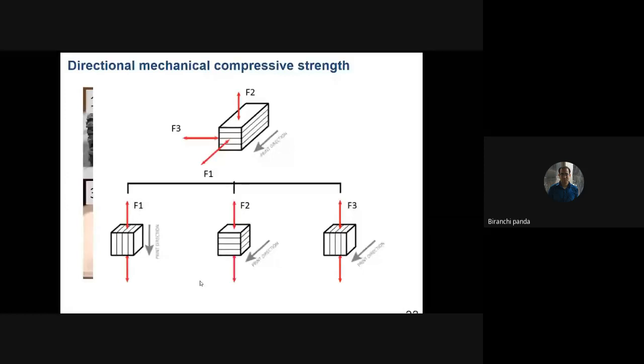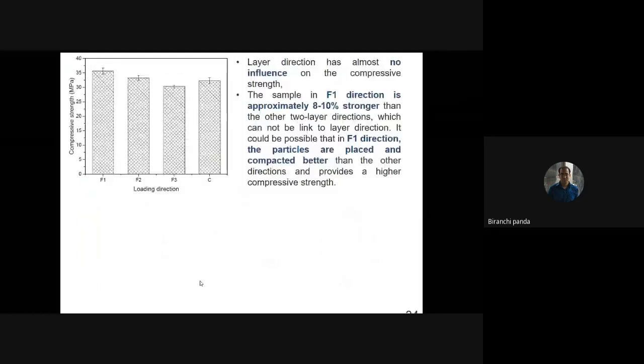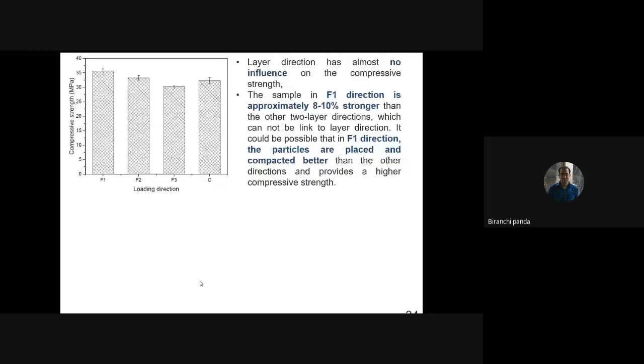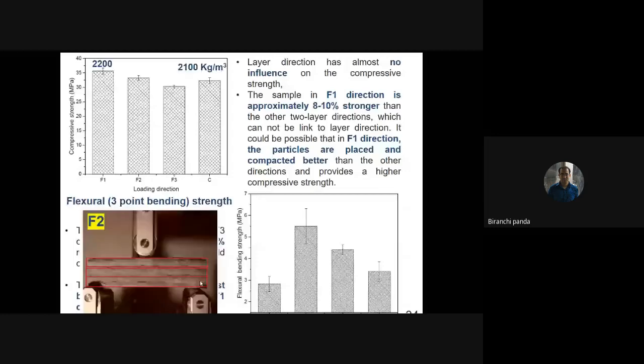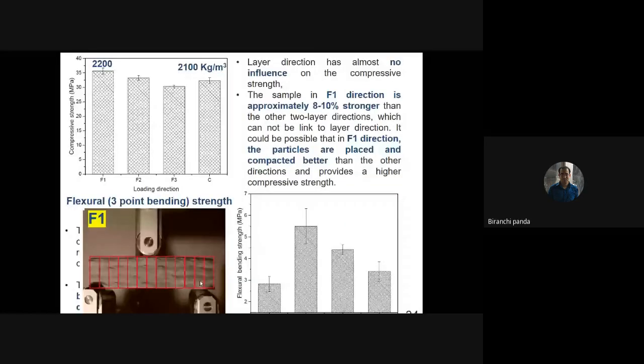But fortunately, we didn't see any kind of anisotropy. I will say it's not much anisotropy, because compared to the casting that is mentioned as C here, the property in three directions is almost similar. Though there is a slight variation in the property, this property is quite similar to the casted sample. But what is most important, when you are going for 3-point bending testing, either the layers will be in this direction or in the same direction of loading. So when the layers are in the same direction of loading, another property comes into picture that is known as interface bond strength.